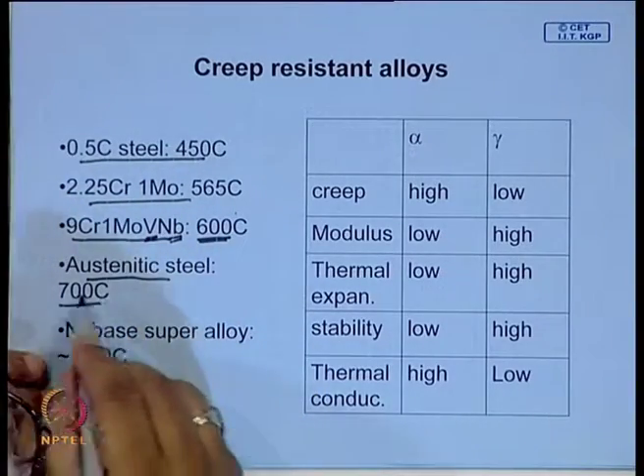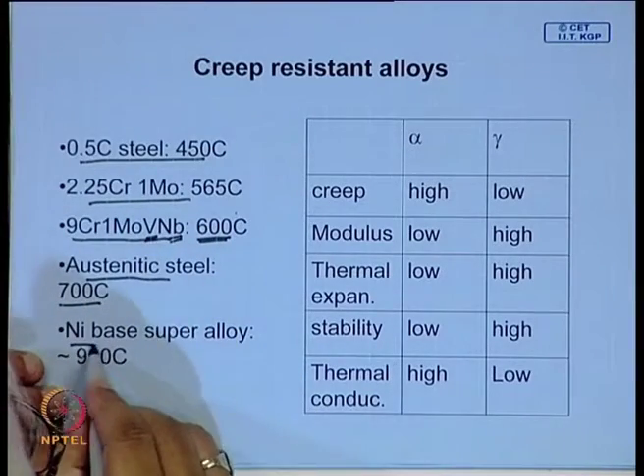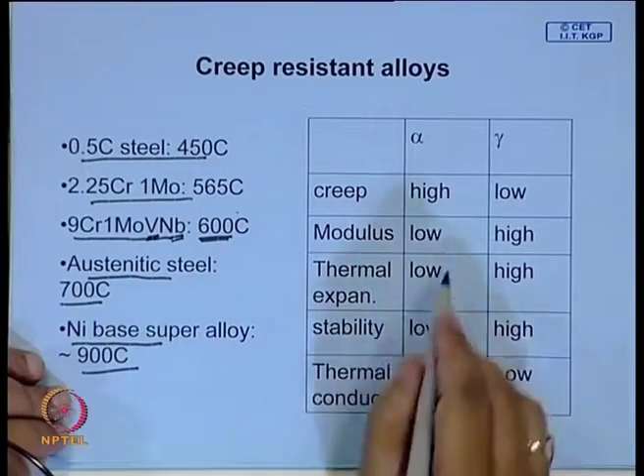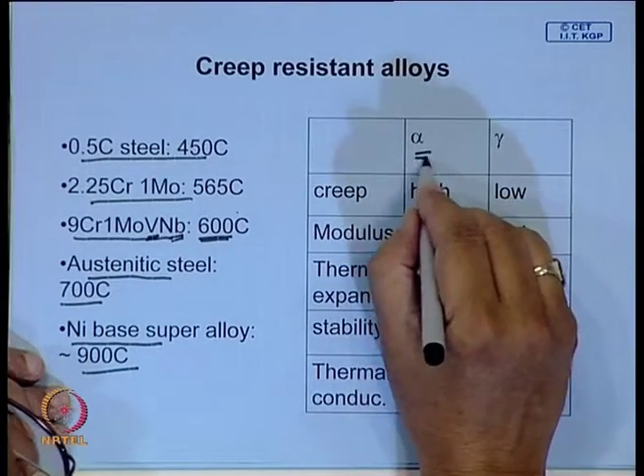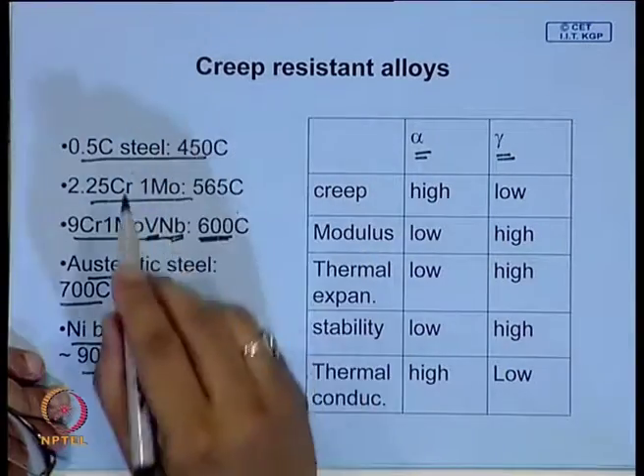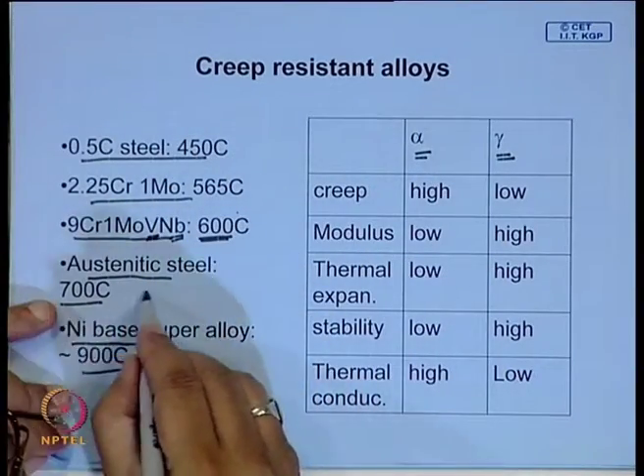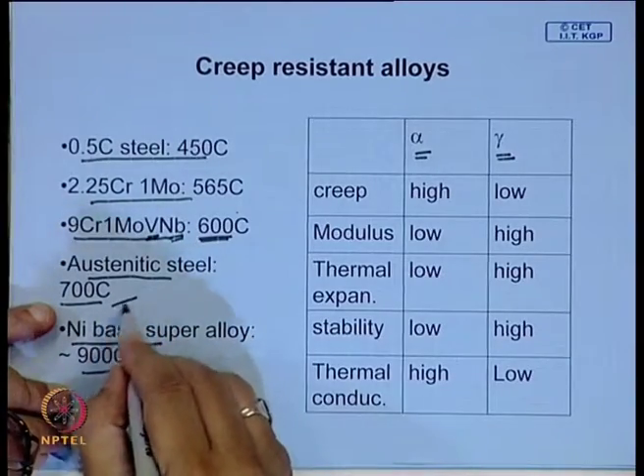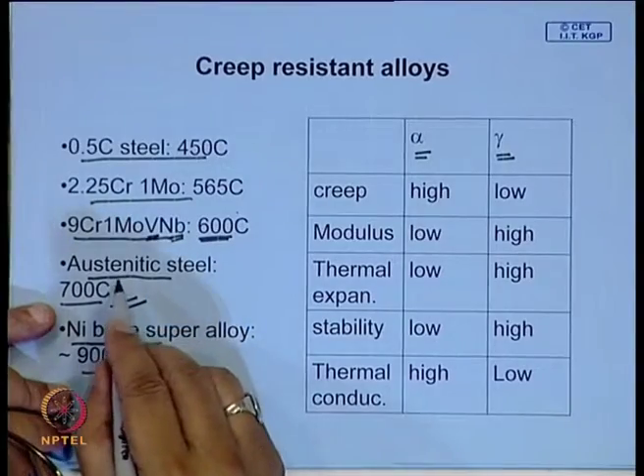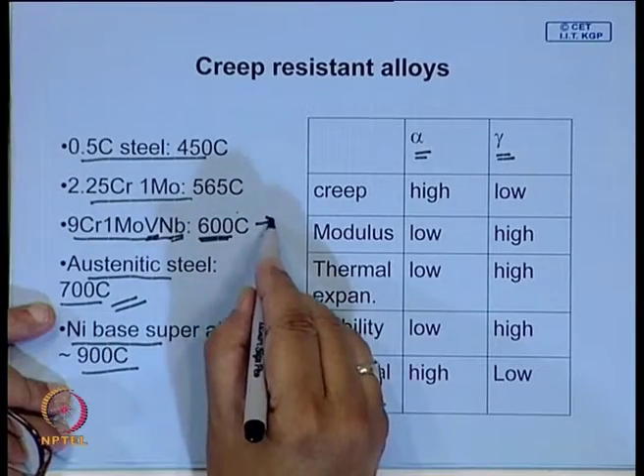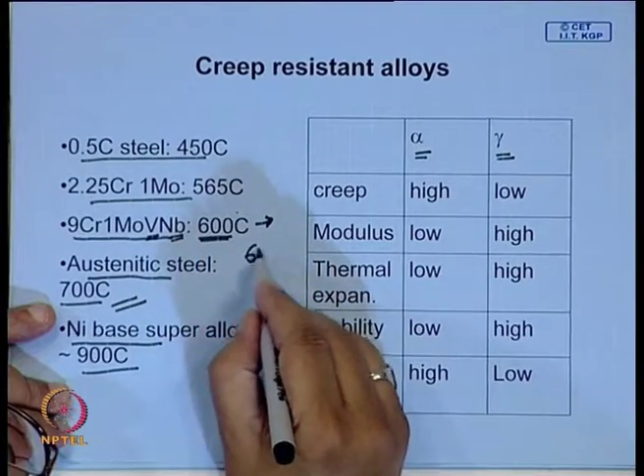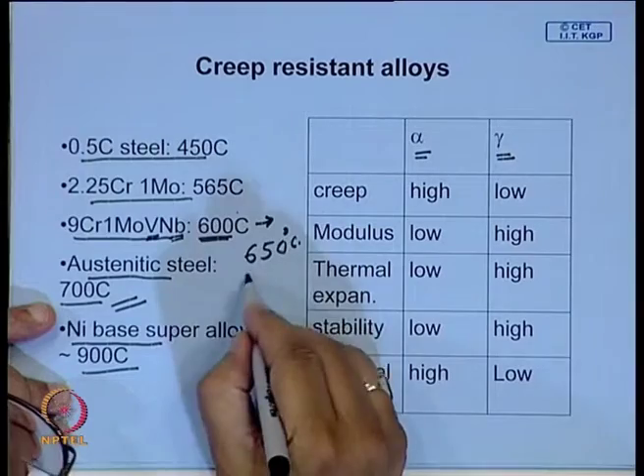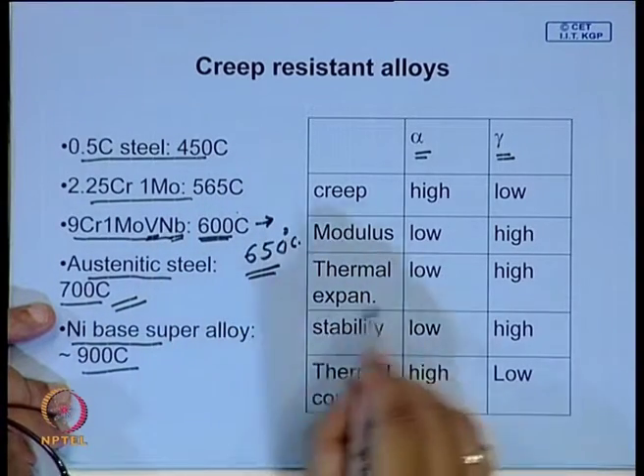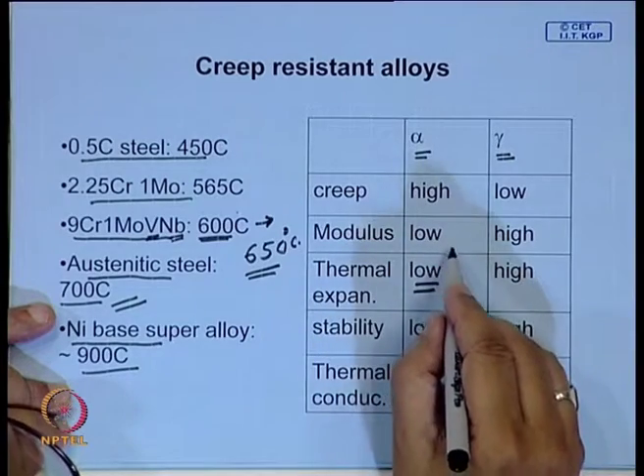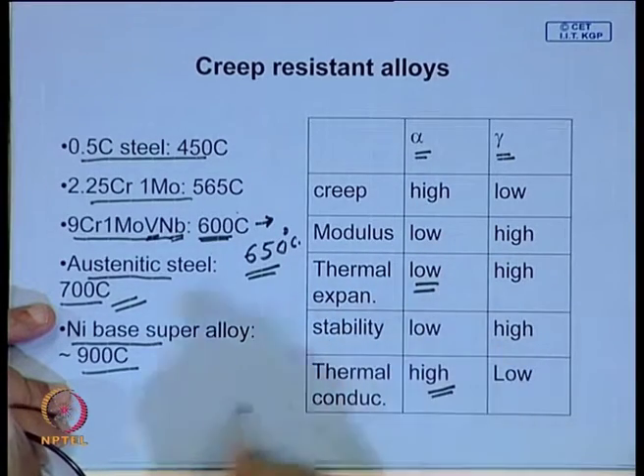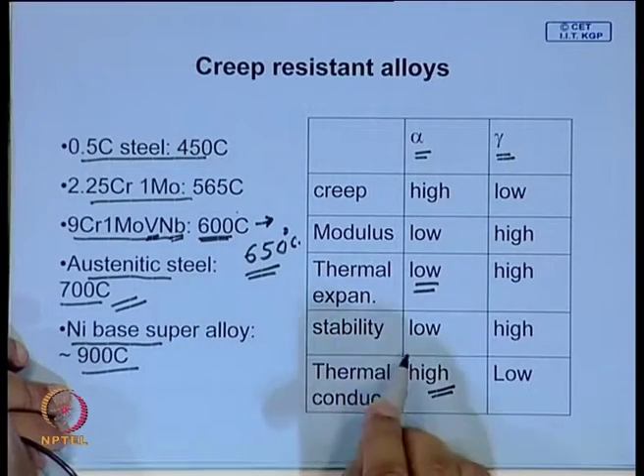Austenitic steels have good creep resistance, and at higher temperature you go for nickel based super alloy. There is often a debate whether ferritic steel or austenitic steel is better for creep resistance. No doubt, at a higher temperature where phase stability is considered, for austenitic steel you do not have an alternative. This has higher temperature capability, but for ferritic steel it is possible to improve its temperature capability to 650 degree centigrade, and it has certain advantages, like low thermal coefficient of expansion and higher thermal conductivity, which are also quite important.